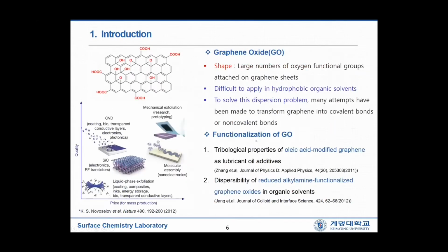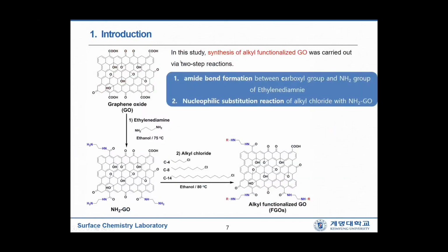Functionalization of graphene oxide. In this study, we functionalized the graphene oxide with various alkyl chlorides by the next two step reactions. The starting materials are graphene oxide and ethylene diamine. The first step is amide bond formation between the carboxyl group and the amine group of ethylene diamine. The second step is nucleophilic substitution reaction of alkyl chloride to aminized graphene oxide.